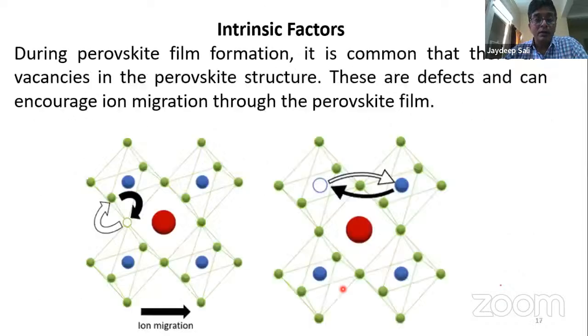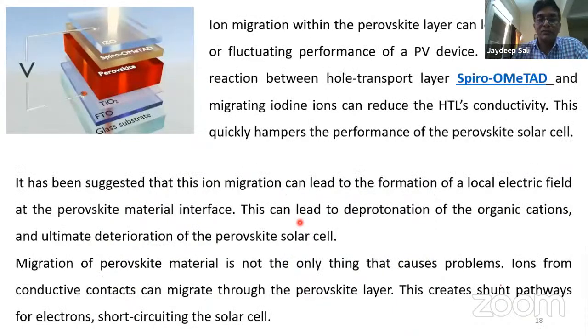Okay, and there are some intrinsic factors, as I have told you, that if the temperature goes high, then it can also lead to degradation of the perovskite. So during perovskite film formation, there are vacancies in the perovskite structure. As you can see here, there is one vacancy, here there is one vacancy. So at high temperature, it can lead to diffusive movement of different ions in the perovskite, and it can cause the deformation or the degradation of the perovskite phase.